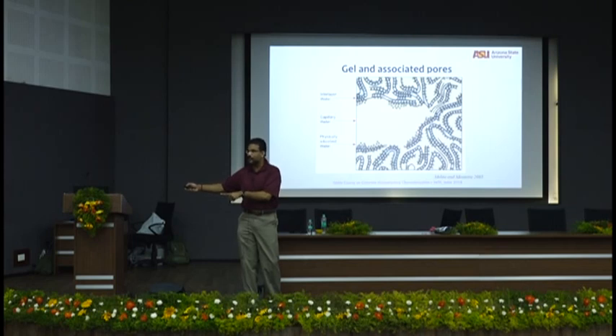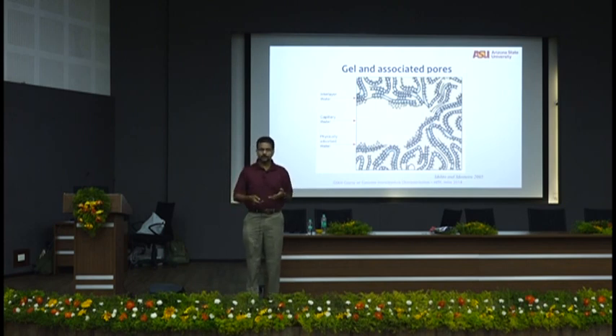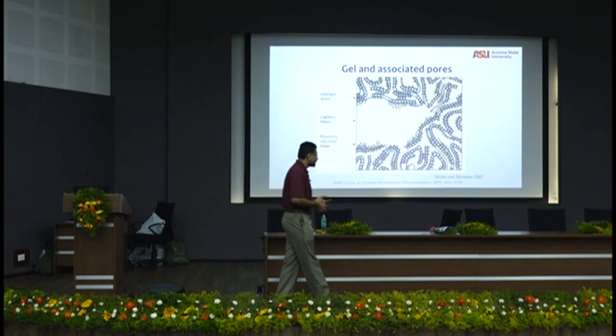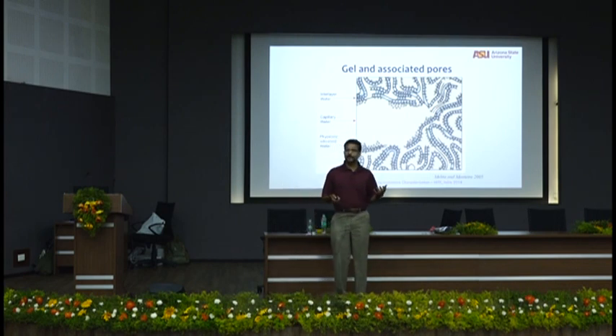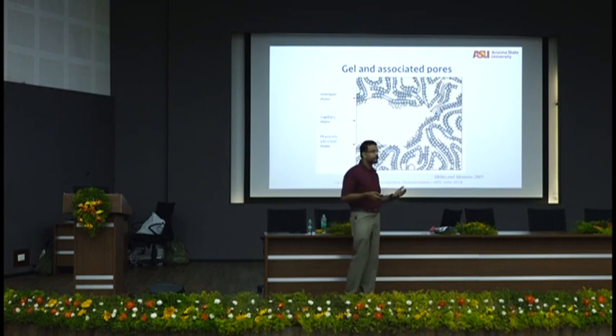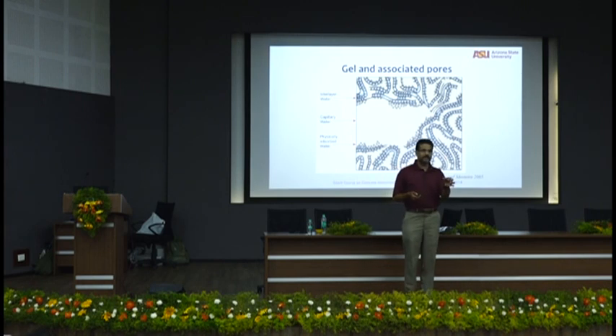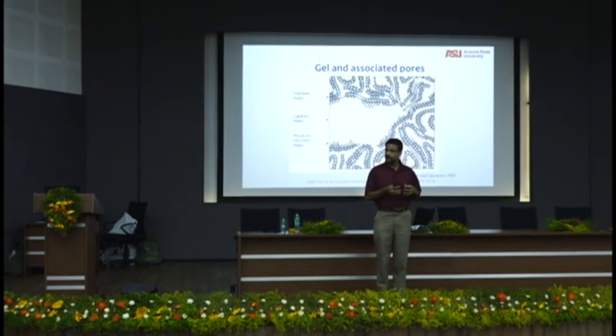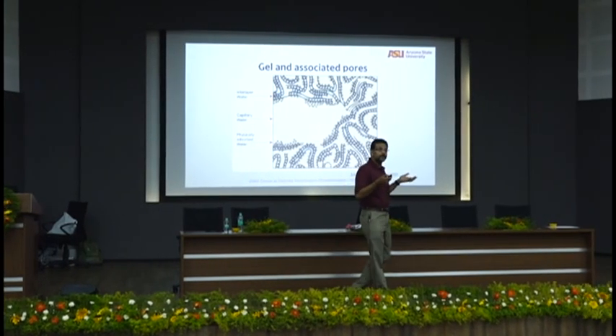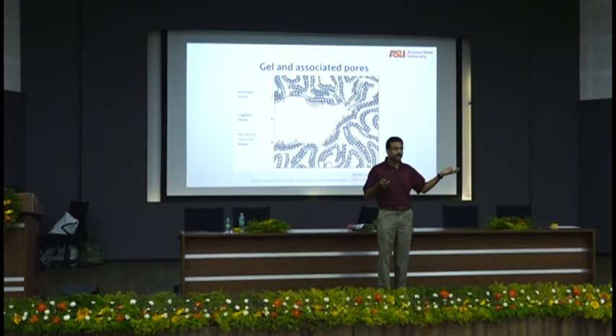Drying sequence will cause cracking, shrinkage cracking, which you will think, oh my God, my pore structure was so good. That is one reason why, have you heard of people saying, oh, I had fly ash in my concrete and it has a lot of drying shrinkage? What does fly ash do? It makes the size of pores small, pore size refinement. When water goes out of the small pores, stresses are going to be higher.